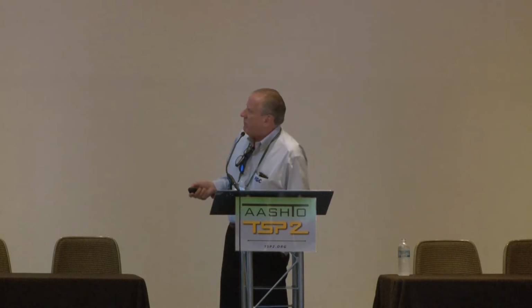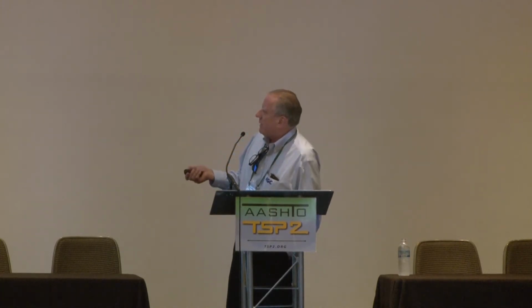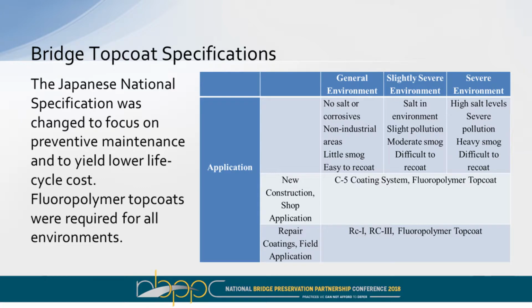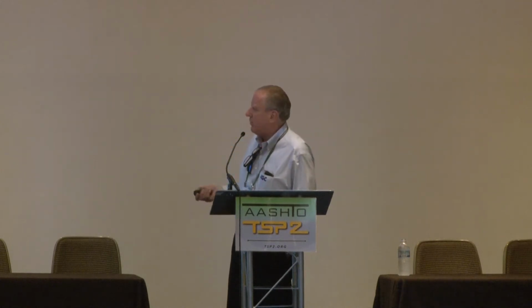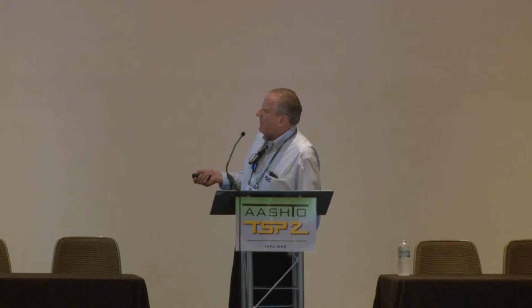Now by 2005, this has changed. Basically what they're recommending now is regardless of the environment, they're recommending the fluoropolymer top coats on the coating system. So most of the bridges in Japan that are being repainted today and are being built today are going to be coated with a fluorinated top coat. And again, it's going to be a similar three-coat type of system with a zinc primer, epoxy, and then a fluorourethane top coat. And you can see here, this is a shop application product, and this is a repair or for field application. And they have slightly different application techniques and slightly different requirements. You might formulate the coating for field application to be brush applied in certain cases. So you'd have to reformulate somewhat in there.